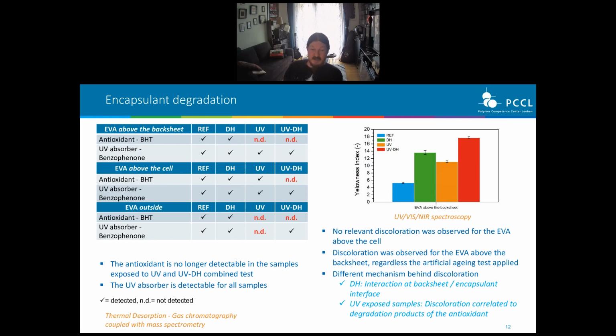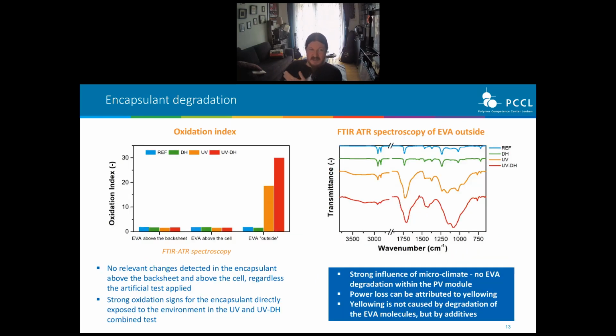But when we UV expose the samples, the encapsulant actually discolors, and this discoloration is correlated to degradation products of the antioxidants. The strongest discoloration you usually find where you don't have any antioxidants left in your PV module, causing this degradation mechanism. Let's take a closer look. How is the material degraded?